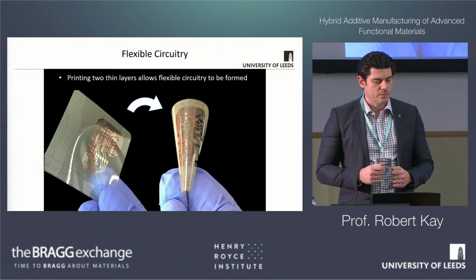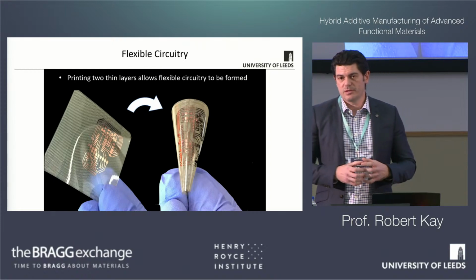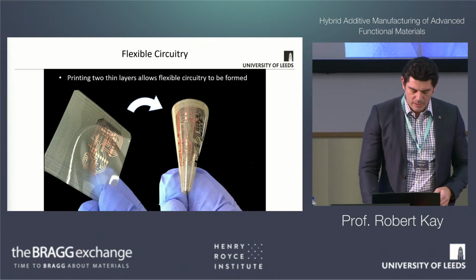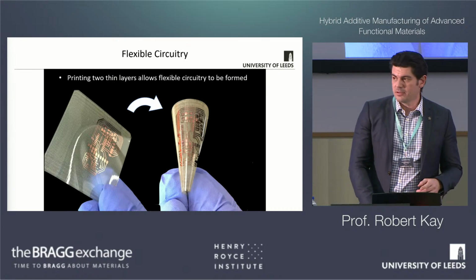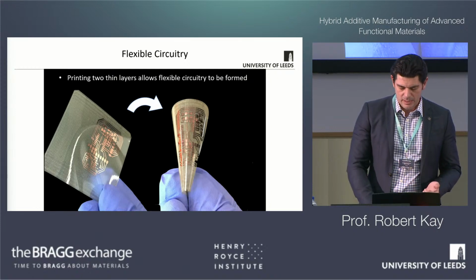We believe we now have a chemical adhesion rather than just a kind of printed mechanical adhesion here. So we're quite delighted to see that by printing 2 45 micron layers, so a part that was about 90 microns thick, so the same thickness as human hair, was very, very flexible.